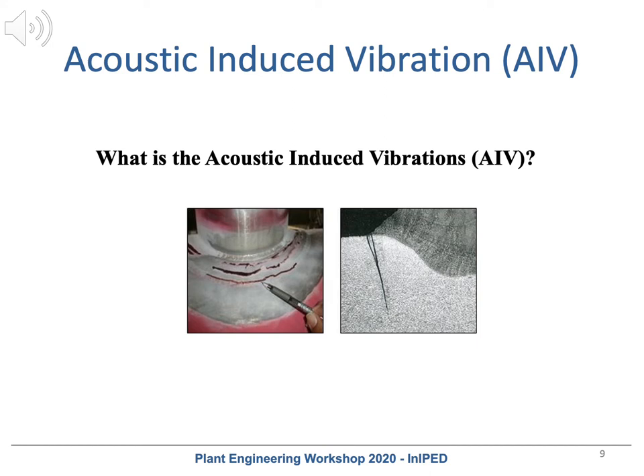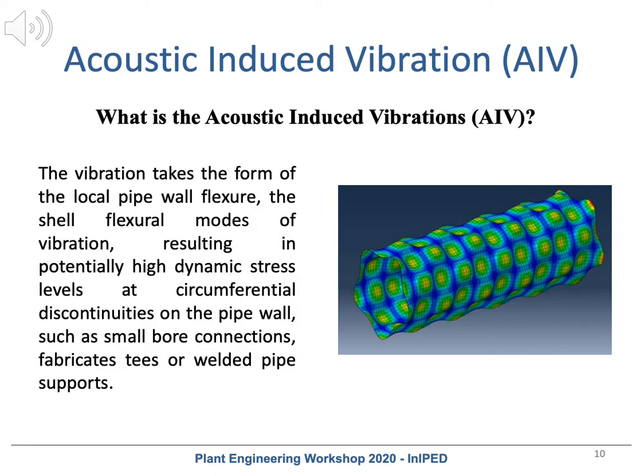The objective of the acoustic induced vibration study is to assess the piping system and to investigate recommendations to minimize the likelihood of failure of piping and piping components due to high-frequency acoustic excitation. Piping vibration can cause metal fatigue through different excitation mechanisms. One of those is acoustically induced vibration. In gas systems, a high level of high-frequency acoustic energy can be generated by a pressure-reducing device. The pressure-reducing process induces turbulent pressure fluctuation in the flowing medium, which in turn excites the downstream pipe, causing stresses and potential fatigue failure.